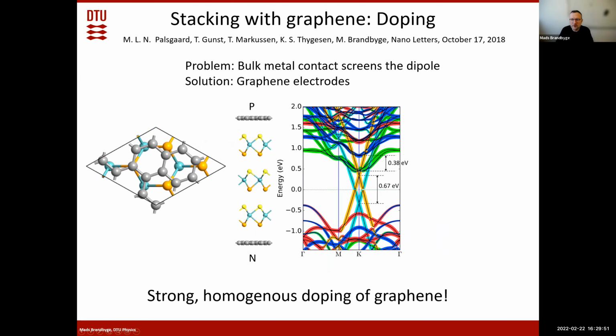The first thing which became clear to us is that if you just put metal contacts on this structure, then it will actually screen out the dipoles. We started to do that and gave up, and then replaced the metals with graphene, because it turns out that graphene will not destroy the device. It will not screen out the dipoles, and actually the dipoles will introduce a big doping in the graphene, which we also like to have.